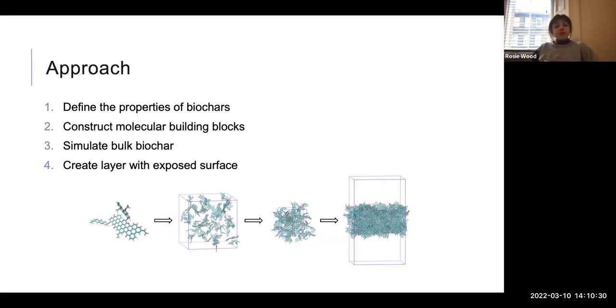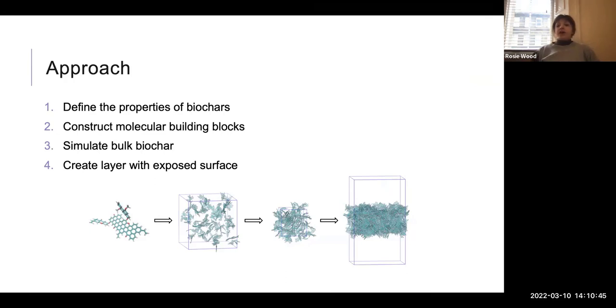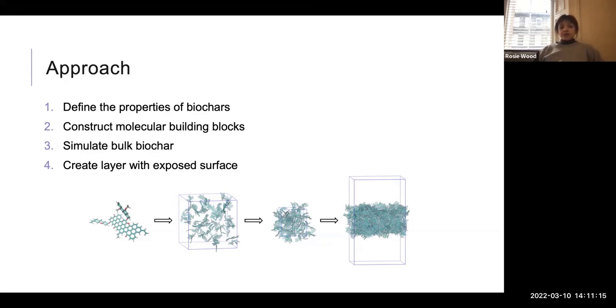Hopefully that's everything you need to know about molecular dynamics simulation to understand my work. What I've been doing is simulating biochars — creating molecular models of biochars. How I've been doing it is: first I defined the properties of the biochars I want to model; I then created molecular building blocks, which are molecules representative of those biochars; I then used these to simulate a bulk biochar that is periodic in X, Y and Z; and then I created a layer with an exposed surface, which is what I can use to study adsorption.